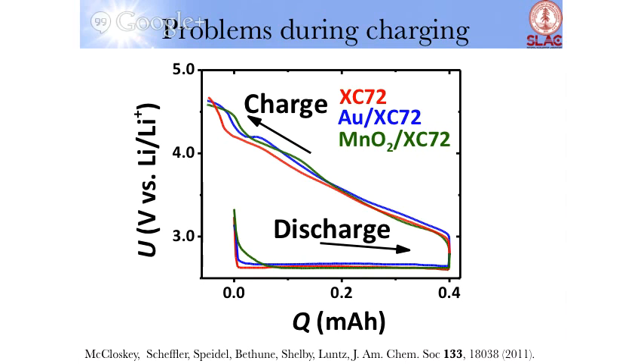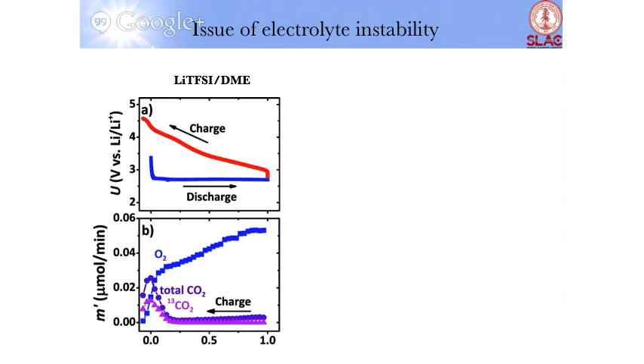We put a picture together based on essentially two experimental observations. What we have here is a discharge and charge curve, and IBM was able to track the gas products. Initially, the dominant reaction was oxygen — so when you charge up, you predominantly get oxygen. But then at the end, you get some CO2. CO2 can come from two possible ways: from the carbon on the electrode, or from the carbon in the electrolyte. Using isotopic labeling, they showed it seems to be half and half — half from the electrode and half from the electrolyte.